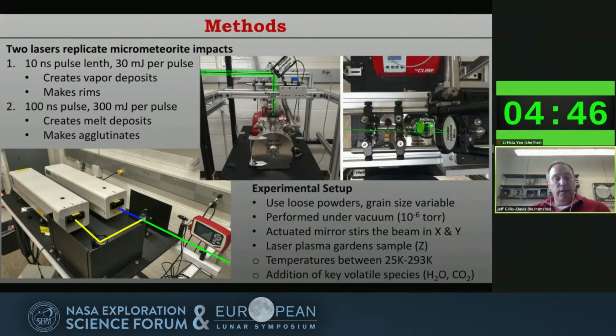So in the image below that, you'll see there are 2 lasers. The blue one is the short pulse. It goes through a beam splitter and then into the chamber. The other laser bounces off and gets combined with that pulse, so we're hitting the sample at the same time. The laser energy is then redirected, in the top images, down into a vacuum chamber. So our experiments are done under vacuum.